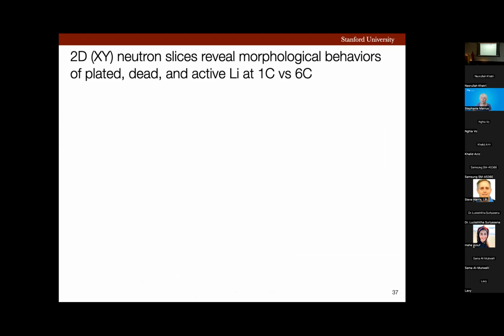Now let's look at the 2D top view or XY neutron slices that reveal different morphological behavior of plated, dead, and active lithium at 1C versus 6C. But first, how was I able to differentiate these three forms of metallic lithium in my battery in the first place? As I just mentioned, I collected data in the charged and the discharged state. So any lithium in the battery in the charged state corresponds to plated lithium. And the residual lithium in the battery in the discharge state corresponds to dead lithium. It is dead because it's irreversibly plated. It had a chance to go back to the cathode, but it didn't. So it stayed there, it became dead. And these two were measured.